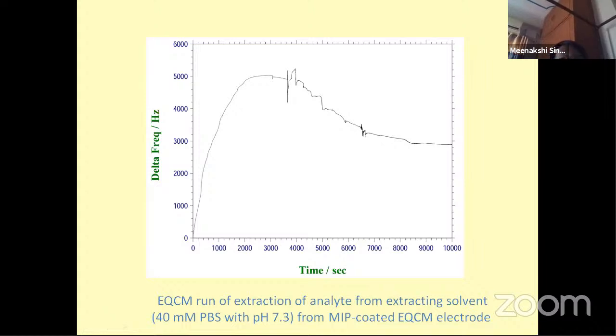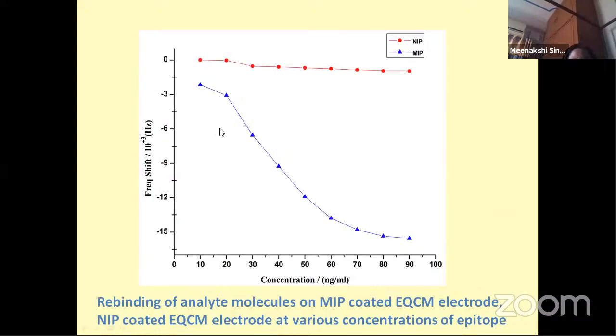And on the electrode itself, for the extraction process, we have used PBS, phosphate buffer solution, with pH 7.3 and ionic strength 40 millimolar. And you can see the increase in the frequency. That means here on your electrode surface, the materials are being released. So this is the proof that the extraction is complete. When it levels down, we stop the extraction. And now you can see the binding.